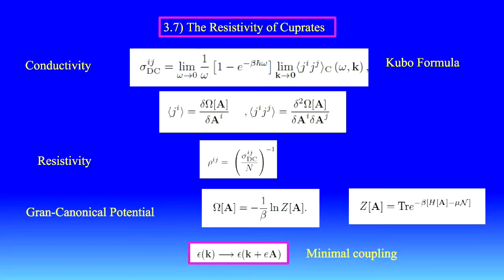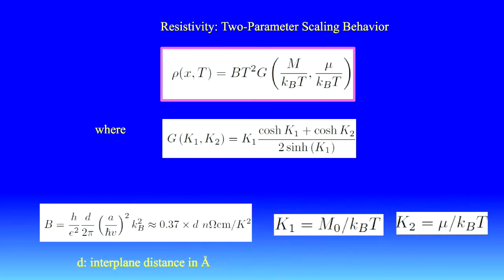So we just use Kubo's formula with this expression. We obtain the current correlator from the grand partition function, and the resistivity is just obtained by inverting the Kubo result. And omega is given by this, so I plug this in here. Thereby I can show that in any phase, the resistivity has this expression here, where G is this function, K1 and K2. And B is given by this.